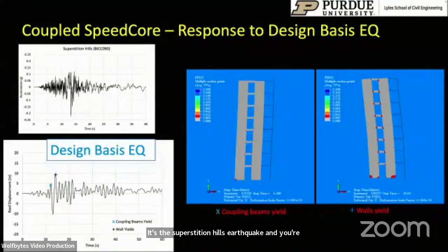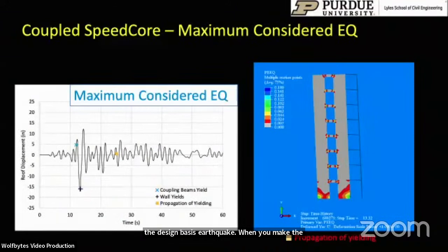We scaled the ground motion to be a design basis earthquake, and what we found was that all you were getting was some yielding in the coupling beams along the height and some yielding at the base of the walls, which is what you'd like to see for the design basis earthquake. When you make the earthquake larger, by changing it to the maximum considered earthquake, the response shows that you get more yielding of the coupling beams and it propagates along the height of the structure, which is what we want.